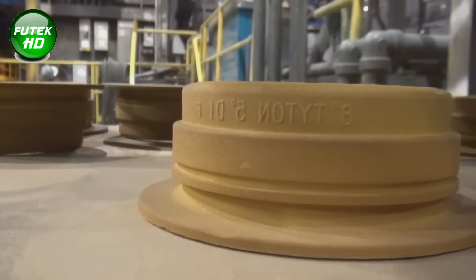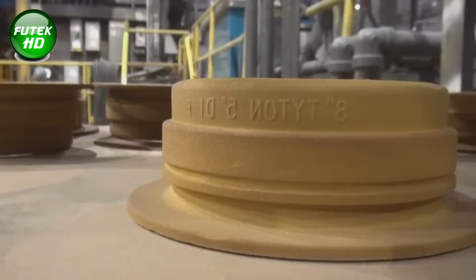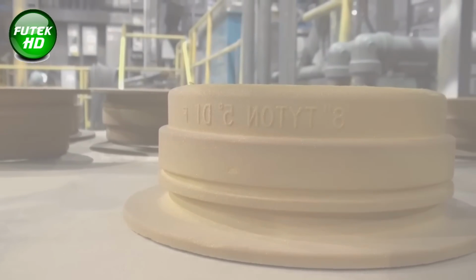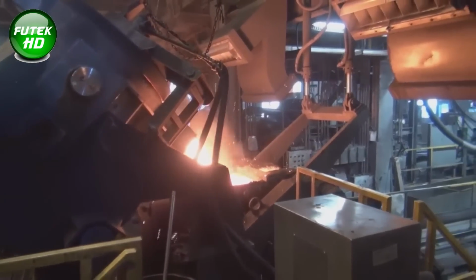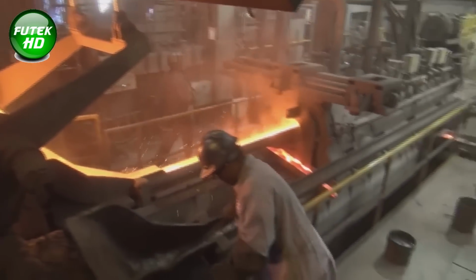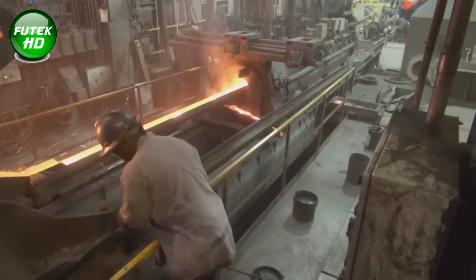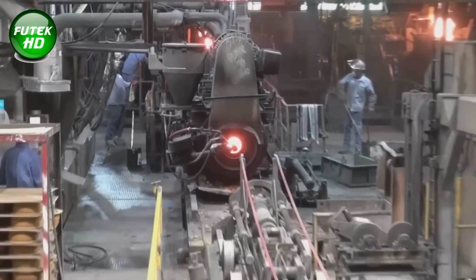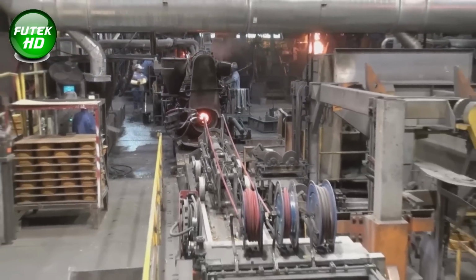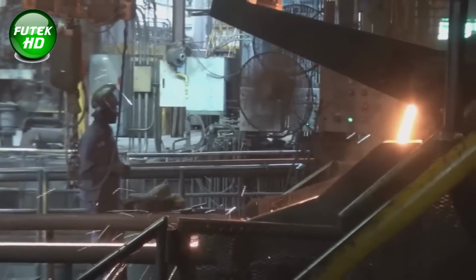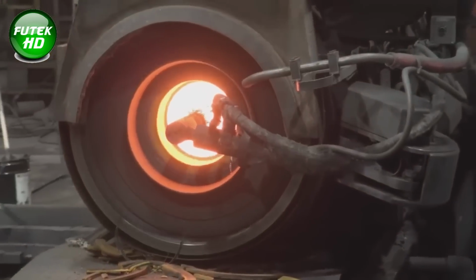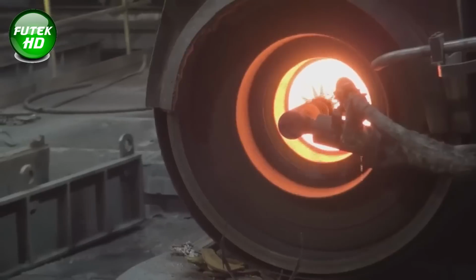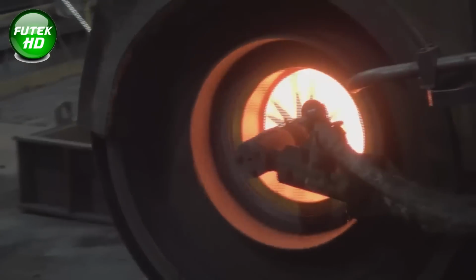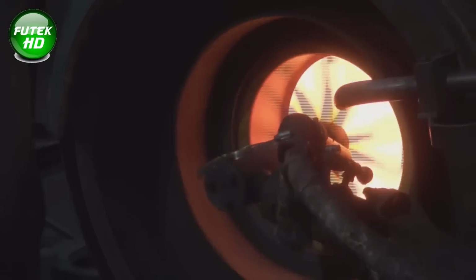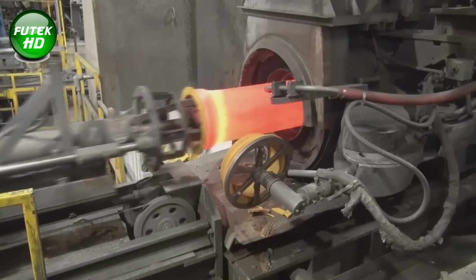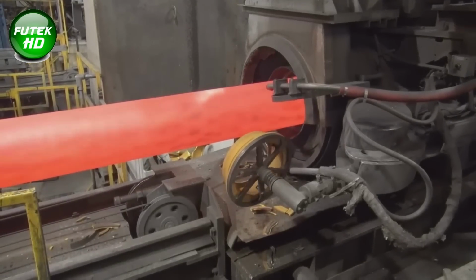The centrifugal force generated by the high-speed rotation of the mold pushes the molten iron against the mold walls. This force ensures a uniform thickness of the pipe wall while expelling lighter impurities, such as slag and gases, toward the pipe's interior surface. These impurities have minimal impact as they remain within the pipe's wall and do not affect structural performance. The inside of the mold is specially textured with a peen surface, which helps the molten iron adhere to the mold walls and prevents splashing. This reduces defects and ensures a smooth casting process. The casting time varies between 30 and 90 seconds, depending on the pipe size and class.